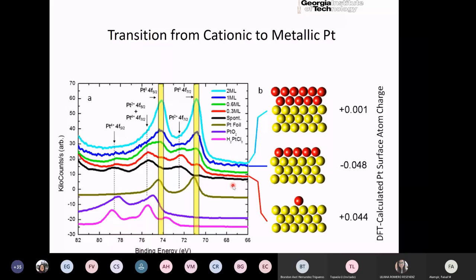The first thing is that we wanted to compare the activity and stability of these graphene templated platinum monolayers, and compare them to the non-graphene templated cases. And we find that the overall behavior is very similar between the two cases. So on the left here, you can see the plots. On the left panel, the GR stands for graphene. So whether you have graphene as a sandwich in between platinum and gold or not, the overall behavior as a function of the number of monolayers is very similar. Okay, so that's just something to keep in mind.